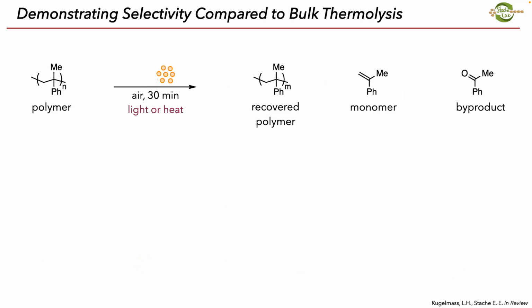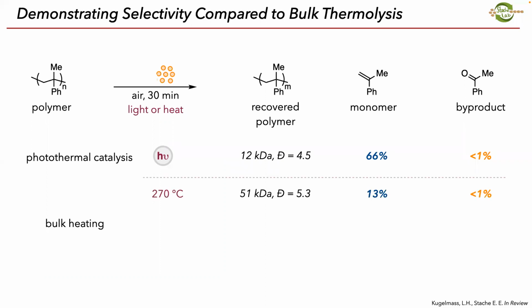And so we wanted to compare our results of using this idea of photothermal heating to what would happen in bulk heating. Under our system, we get 66% of the monomer, the leftover being recovered polymer, and less than 1% of this oxidized byproduct. So we're not seeing those bimolecular side reactions to complicate our product stream. If we heat this up under similar conditions to 270 degrees C, so this is now bulk heating, we do see polymer depolymerization. We get 13% of monomer in the same amount of time. So not as much. We're actually getting hotter in the photothermal catalysis example. We still don't see any byproduct.